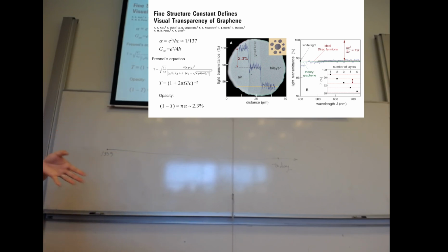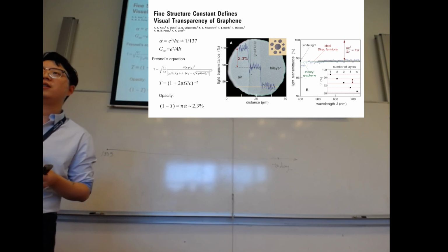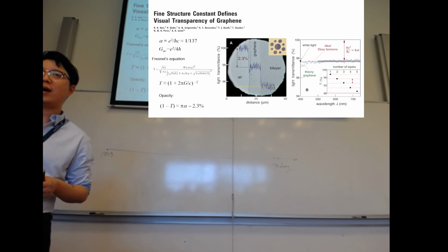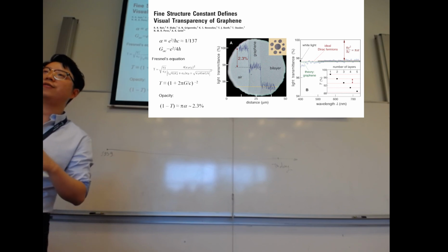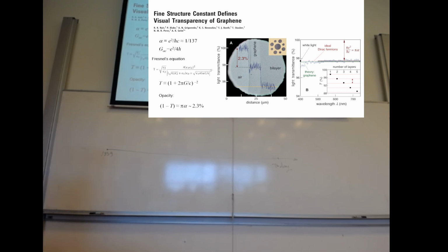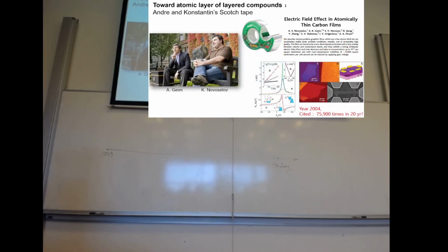And also, you have to be lucky to use a good wafer, because when you put these thin films on top of a silicon oxide wafer, you have light incident twice, from the top surface and at the interface of silicon oxide and silicon, and then there is destructive interference of light. Also, then you will get some kind of competition between the interference. So luckily, Geim and Novoselov were using a 300 nanometer thickness wafer.